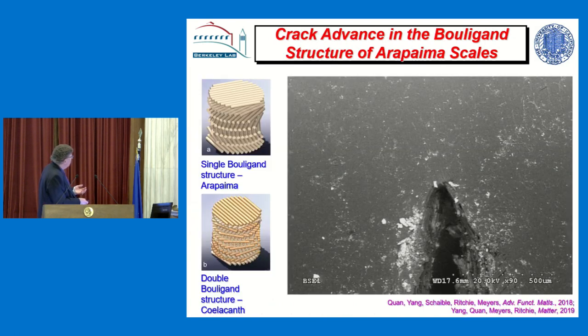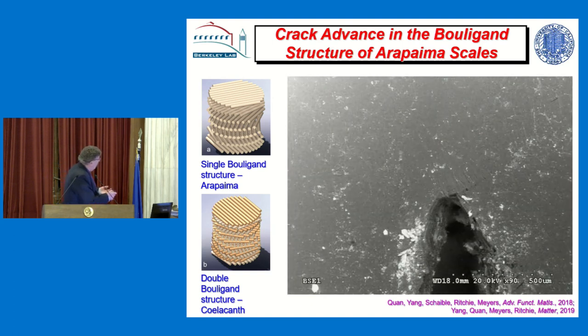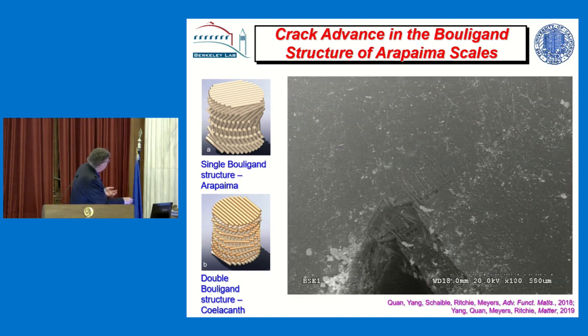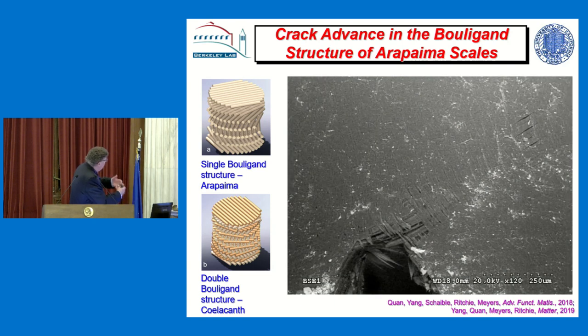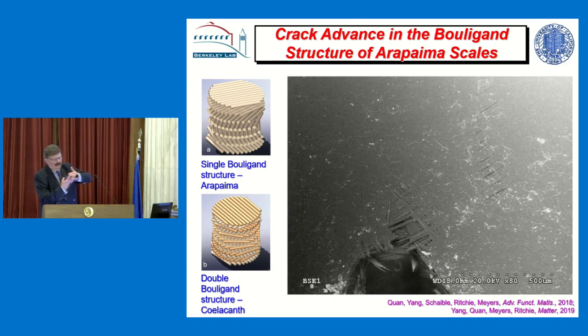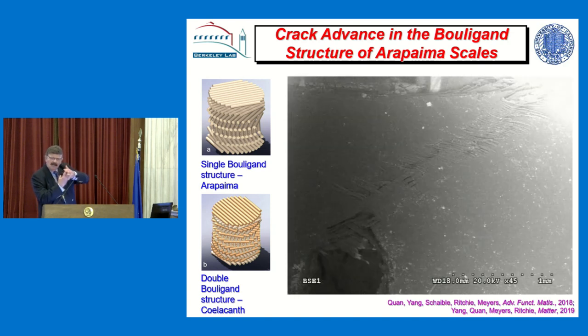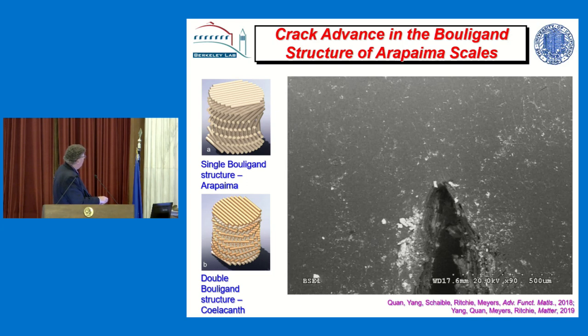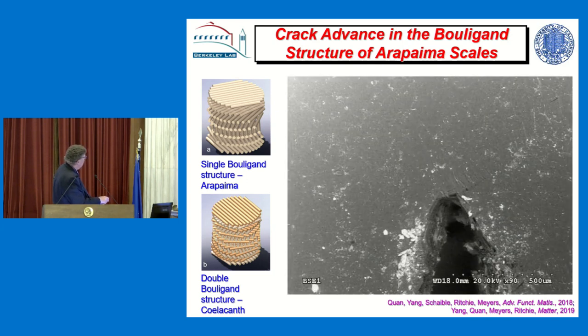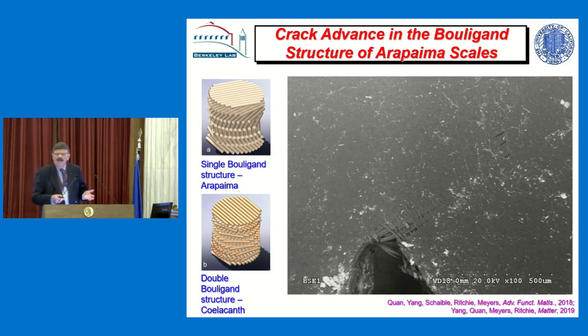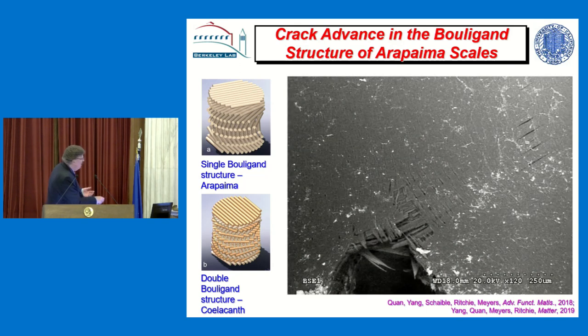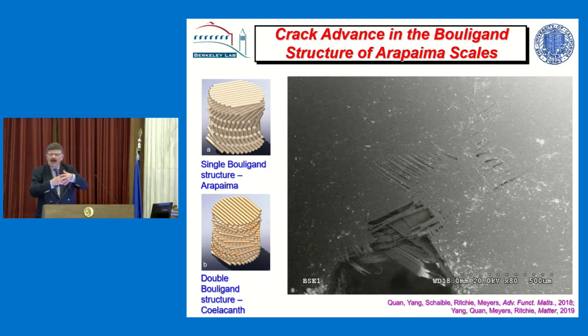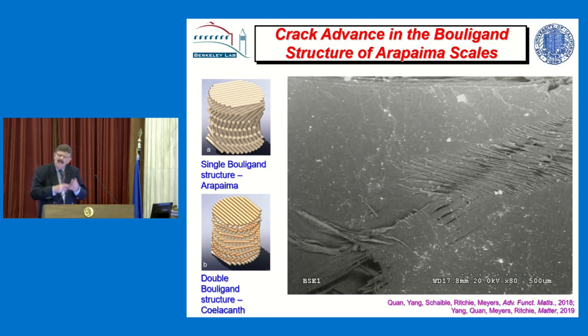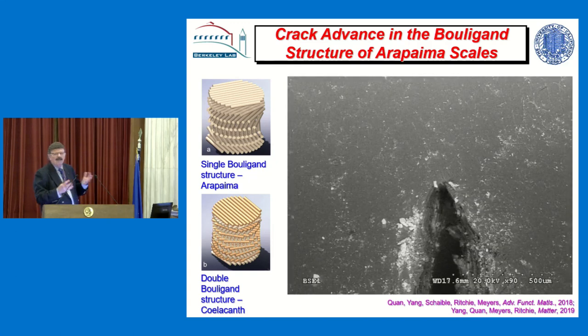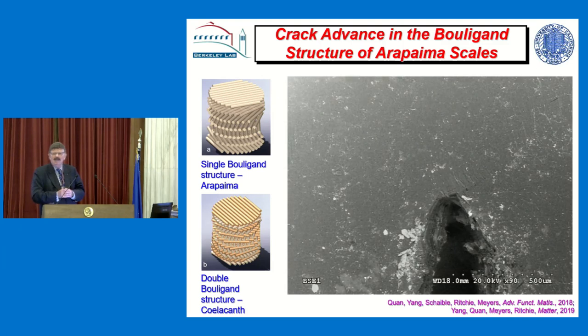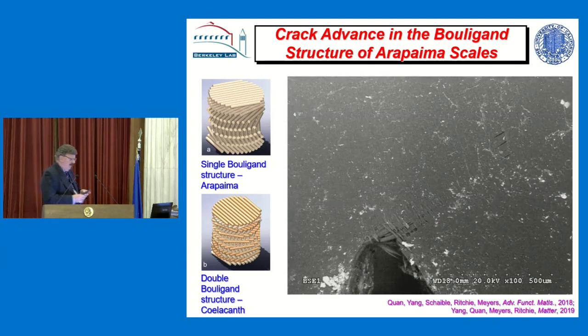of these fish scales. You can see a picture of it here. This is the crack, but you'll see all these cross-ply lines that interact. Very effective way. It's the layers rotating and interacting that causes a great deal of toughness. Most fish today have what's called a single Bouligand, but if you look at some of the fossilized fish, they actually have double Bouligands, where they have two layers in opposite directions that rotate in the same level. These are actually even tougher, but they're much less flexible. So the fish is not so flexible, but it's much, much more likely to survive heavy penetration by a predator.